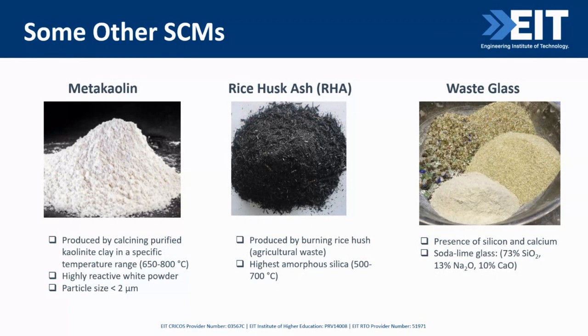There is some research showing that the pozzolanic property of glass is first notable at particle sizes below approximately 300 micrometer, and below 100 micrometer glass can have a pozzolanic reactivity which is greater than that of fly ash at low temperature, low percentage of cement replacement levels, and also after 90 days of curing. Glass, therefore, has the potential to acceptably function as a supplementary cementitious material.